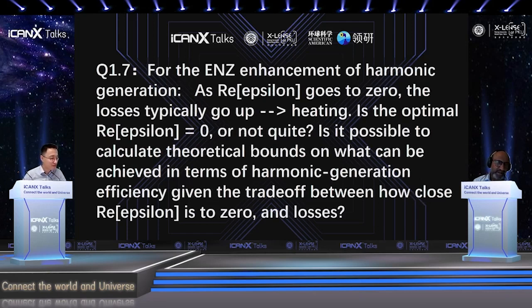For the ENZ enhancement of harmonic generation, as the real part of epsilon goes to zero, the losses typically go up with heating. Is the optimal real part of epsilon equal to zero or not quite? Is it possible to calculate theoretical bounds on what can be achieved in terms of harmonic generation efficiency, given the trade-off between how close the real part of epsilon is to zero and losses?